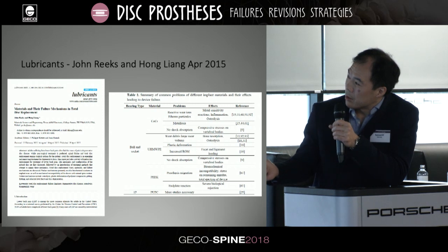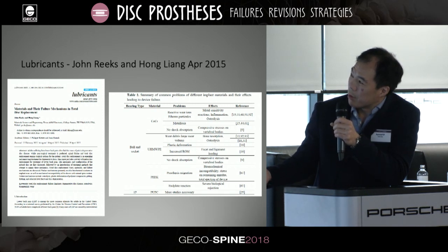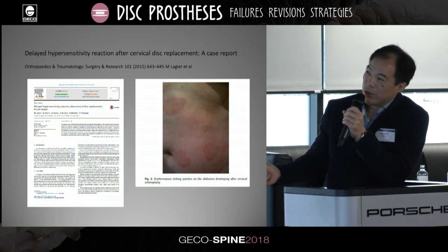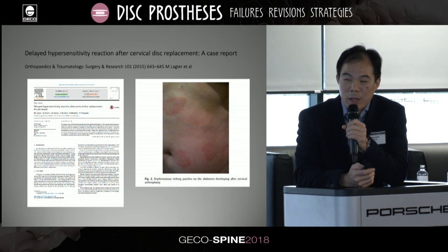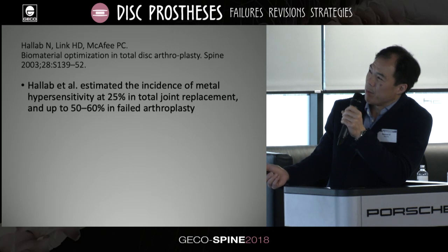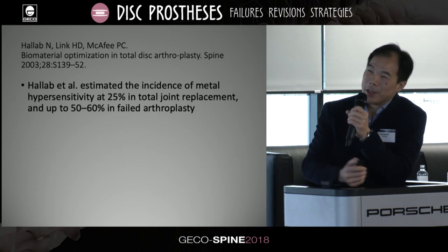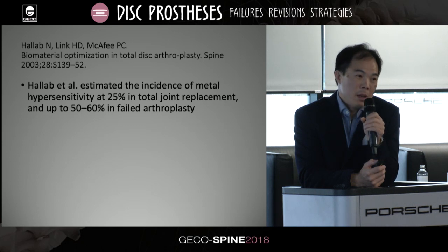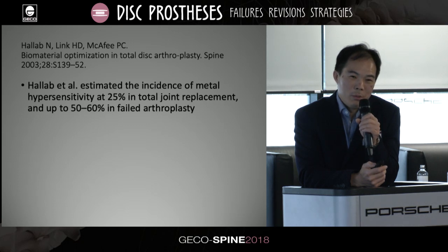I did a literature review on metal allergies and found that various things can cause osteolysis — cobalt-chrome, polyethylene, PEEK, and others. There is a case report of delayed hypersensitivity reaction after cervical total disc replacement with skin changes that disappeared after implant removal. McAfee published findings estimating metal hypersensitivity in about 25% of total joint replacement patients, and possibly up to half of failed arthroplasty patients may be experiencing this problem.